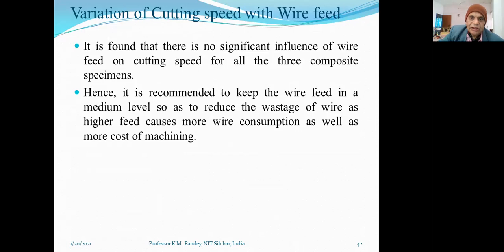It is found that there is no significant influence of wire feed on cutting speed for all the three composite samples. Hence, it is recommended to keep the wire feed at a medium level so as to reduce the wastage of wire. Higher feed causes more wire consumption as well as more cost of machining.